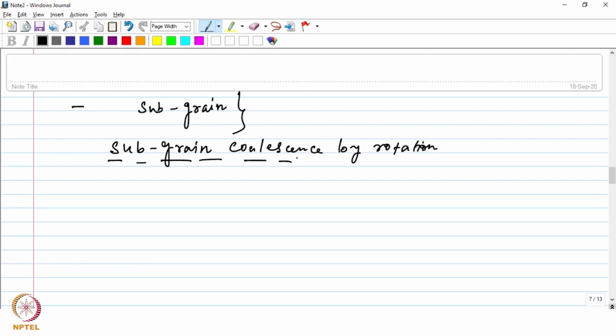So the subgrains can merge or coalesce together to form the nucleus, but for the misorientation across them to decrease, the merger or the coalescence alone is not enough. It also needs to rotate to certain extent so that the misorientation between them can decrease. So that is where the need of the rotation. So a subgrain can rotate and align itself with the neighboring subgrain, and then as the misorientation between these two subgrains due to this rotation comes down, then these two subgrain can merge into one, because now there is no orientation difference between these two adjacent subgrains. Right? For that to happen, one of the subgrains or the subgrains which are taking part in this coalescence process have to rotate.